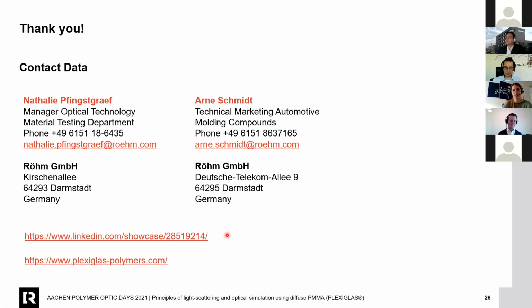Good. I have an additional question. When we try to use this material in practice, we realize that the scattering performance is dependent on molding parameters, on plasticizing and melt flow during molding. Do you have experience with effects like that? Yes, that's the reason why we use the experimental approach. So we are using plastic particles, highly cross-linked plastic particles, as scattering particles.